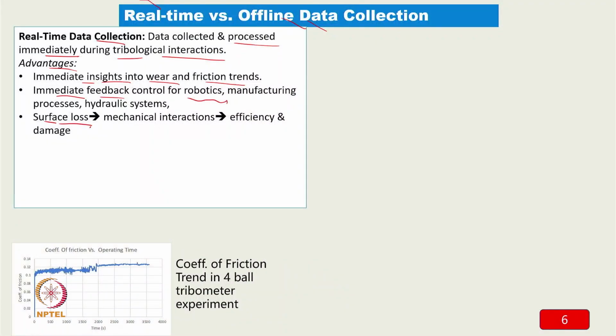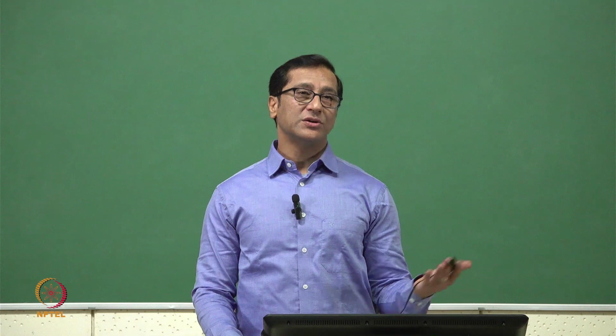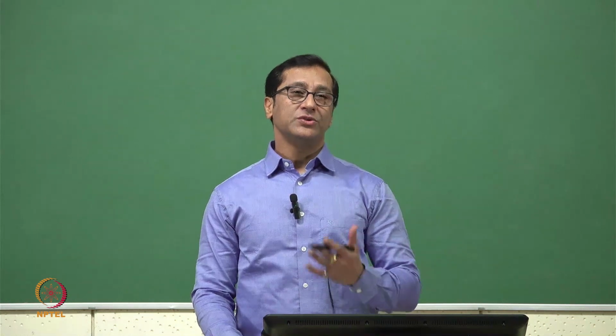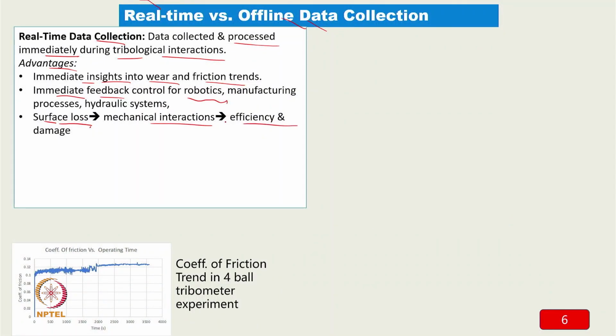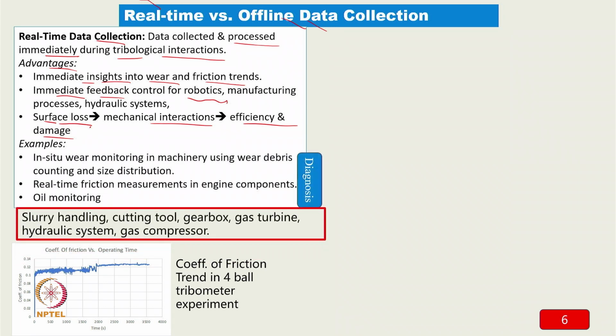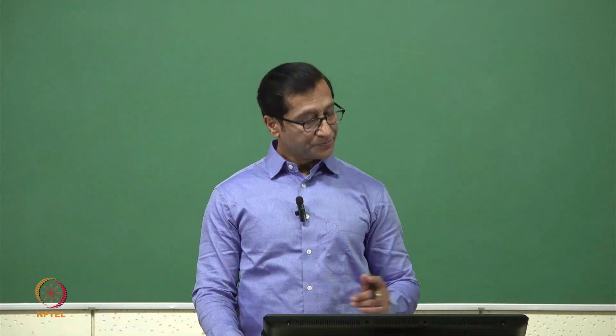That's what I mentioned, that the future is that we should be able to predict the surface in situ, how the surface is changing with time, so that overall results are in our favor. If we are able to do that, then efficiency can be improved and the damage can be reduced to a significant level. I showed in situ measurement of the coefficient of friction, which we did on the four-ball tribometer. You can see here initially the coefficient of friction is roughly 0.1, and with time it has increased to 0.13. So this is very important to see how the changes are happening.